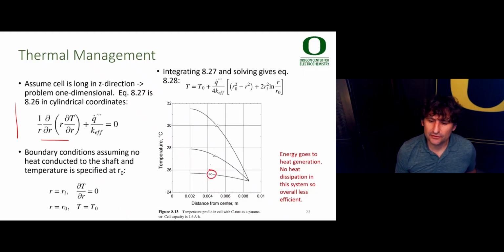So here's an example of different charging rates as a function of distance from the center of the battery, the temperature profile. And you can see there can be fairly large differences in temperature, several degrees, depending on the rate of charge or discharge. In fact, if you charge too fast, the battery could heat up so much that it could explode and catch on fire. Also note that energy goes to heat generation. So the more heat generated, the higher the thermal gradients, the less efficient your charge and discharge process is.